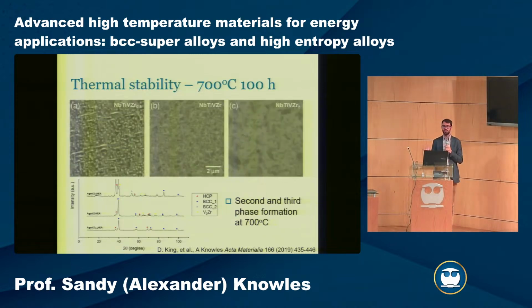If we then thermally anneal it, since we're trying to develop materials for high temperature applications, we need to know what happens through the use temperature. When you process it, you might need different conditions, but also when you're going to use it in, for example, a high temperature nuclear reactor, it's going to sit at temperature for a long time. So we need to know whether it might decompose. In this case, this high entropy alloy, despite all our entropic stabilization, doesn't stay single phase. We do get this decomposition, we do get formation of intermetallics.